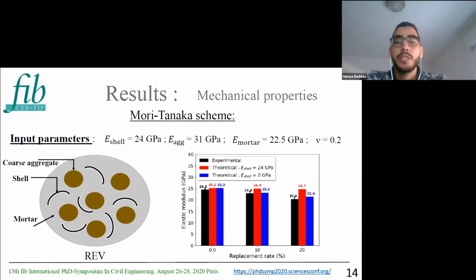So I add to this presentation a simple theoretical part in order to show that if we consider a lack of adhesion between the shells and the mortar, the Mori-Tanaka scheme can provide values equivalent to those found experimentally. So first, the elastic modulus of the different phases are measured. The elastic modulus of the mortar is measured in the same way as the concrete, while the elastic modulus of the inclusions is obtained from the micro-indentation test. The Poisson's ratio is considered equal to 0.2 for all phases.